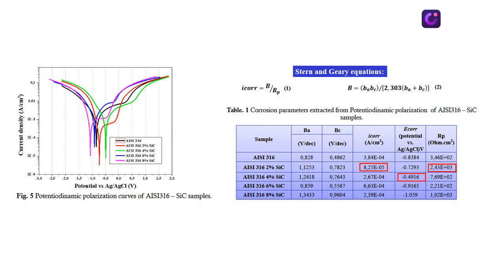In the potentiodynamic polarization results, the sample with 4% reinforcement shows a more electropositive potential than the rest of the samples, followed by the 2% reinforcement and the steel sample. This indicates that the 4% sample offers the best corrosion protection. These results are consistent with those obtained by electrochemical impedance and porosity evaluation.